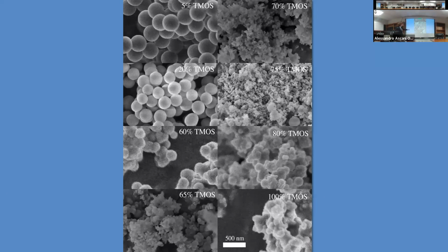However, from 60% to about 75%, we noticed that particles start decreasing in size. Something is clearly going on there. And finally, above 80%, we noticed that the particles are no more, and what we have is just amorphous silica, meaning that we don't have particles anymore, but the aggregation reaction is happening so quickly that it just became straight up amorphous silica.